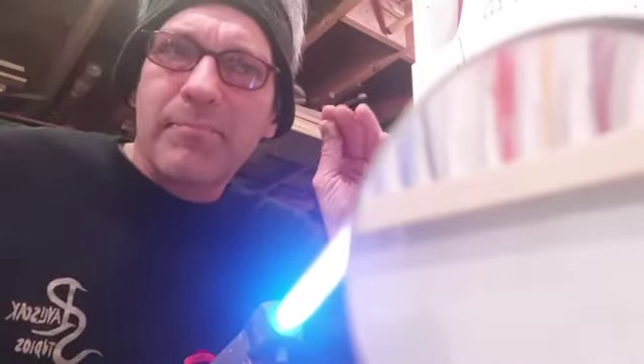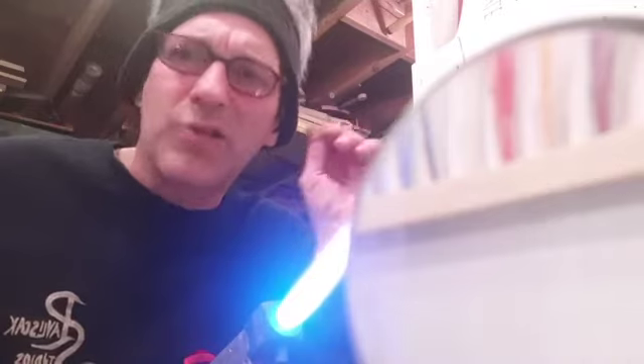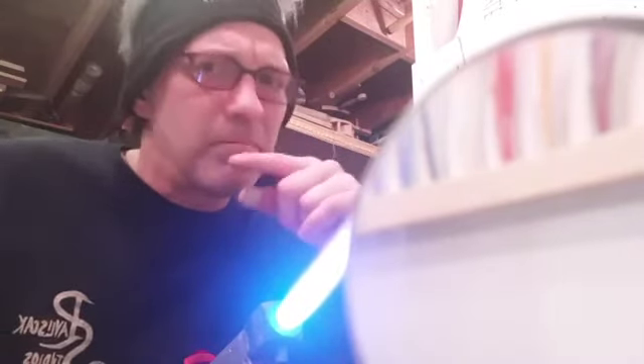The glass just needs to be maintained at that point where it's a solid. It almost will go to a liquid, but you don't want it to be moving. So, at about 960 degrees, bond angles can all correct themselves. This internal stress can come out of the glass, and that's annealing. It needs to be like that for, I'd say, 1 hour per quarter inch of thickness. This is about a 1-inch marble. I usually anneal my marbles for about 2 hours at this size. If I start getting over an inch and a 16th, then I start lengthening the time. But this was about a 1-inch, 1/16th marble, so that 2 hours should be fine.